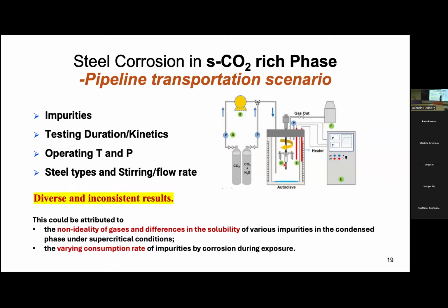The other thing is about the water they introduced. Some groups introduced 10 mL. Some groups introduced, for example, 50 mL at the bottom. And when you introduce acidic gas in this environment, this will serve as what? As an impurity sink, right? Because SO2, H2S, they can all dissolve in here. So we don't know how much is really left there. That's why I think the results, even though tons of work has been done in this area, are diverse and inconsistent. The main reasons are varying consumption rate, varying testing duration, and varying water accumulation at the bottom. So that's a pipeline transportation scenario.